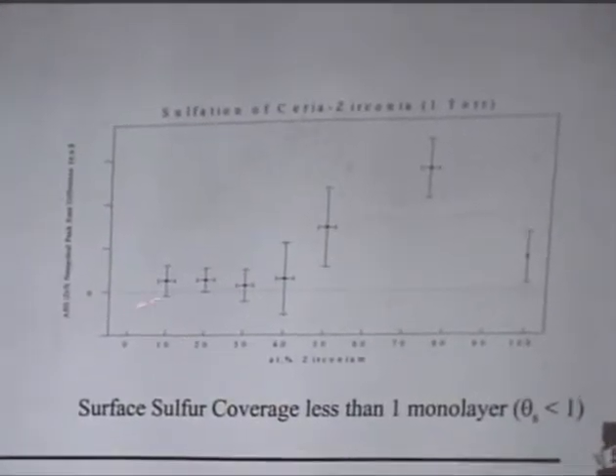Okay, for the mixed oxides, we plotted them as follows. What this represents is atomic percent zirconium from 0 to 100%, and this is the ratio of the zirconium to sulfur peak that we extracted from our data. This is for the low coverages, so probably a tenth or so of a monolayer. And what we see is it's not what we expected to see.